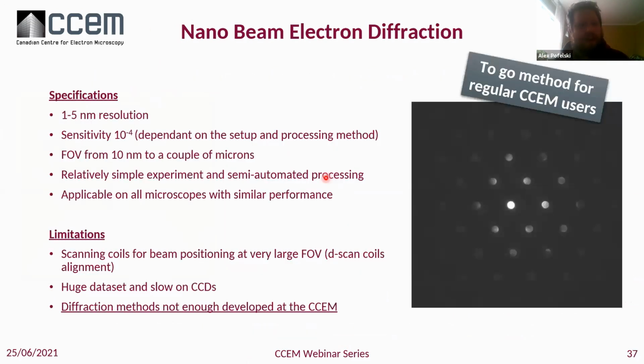So this is my conclusion regarding the diffraction method. In brief, you get something like 1 to 5 nanometer resolution, with sensitivity down to 10^-4. Also, this is dependent on the setup and the processing method, so this might vary between 10^-3 and 10^-4, but usually it is one order of magnitude better than what you get in high resolution imaging. The field of view is 10 nanometers to a couple of microns.